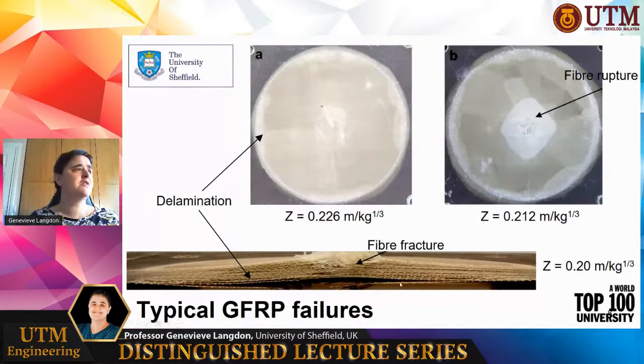And if you take a look at the image on the bottom of your screen, what we've done there is we've taken one of those panels, we've cut it in half, and we're showing you the cross section. And you can see how the layers of material within the composites have come apart, and you can see the gaps which indicate delamination, where that image is showing the blast would have come from the bottom upwards. So what you're seeing is on the tensile side of the structure, if this was purely under bending, that's where the fiber fracture initiates.